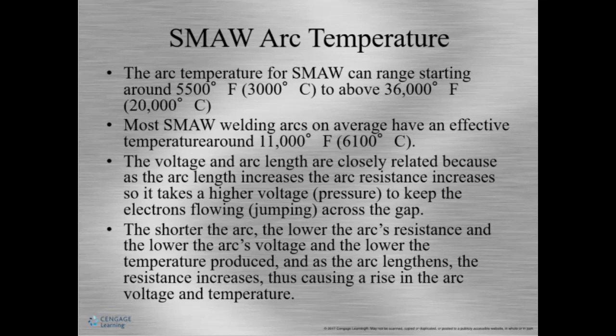The voltage and arc length are closely related because as the arc length increases, the resistance increases. So it takes more voltage or more pressure to keep the electrons flowing across the gap. So the shorter the arc, the lower the resistance, lowering the voltage and lowering the temperature produced. As the arc lengthens, resistance increases and causes a rise in voltage and temperature.